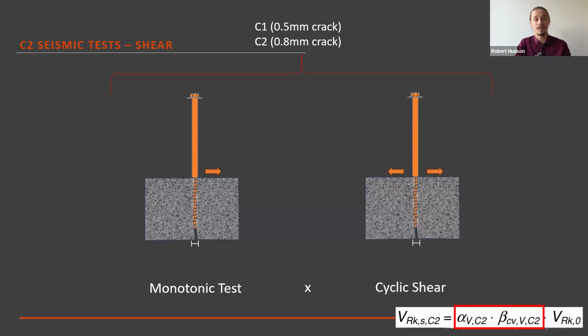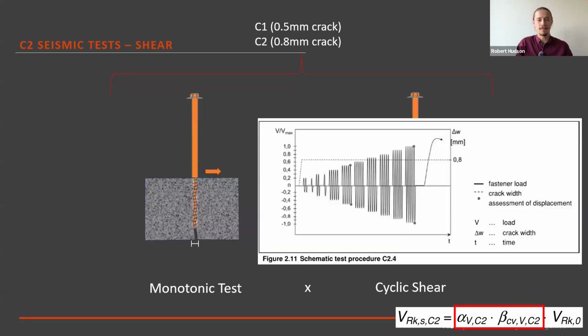Which means that the mechanisms that C1 and C2 are allowing for are actually the same. And with regards to shear capacities, the main difference is just that we're allowing for a larger crack width. And that does have a negative impact on anchor performance, obviously, but that really is the main difference between the two. And then that's actually the test you run for cyclic shear. You're bringing your anchor into negative and positive shear in both directions. And quite often for some anchors you start getting steel failure governing, especially if you're deep embedment, which is a really positive failure mechanism with regards to anchor performance, rather than pry out or anything like that. In general, even when you start putting seismic actions into anchors, shear performance is a pretty reliable mechanism, because at the end of the day, you've got a piece of steel in a substrate.